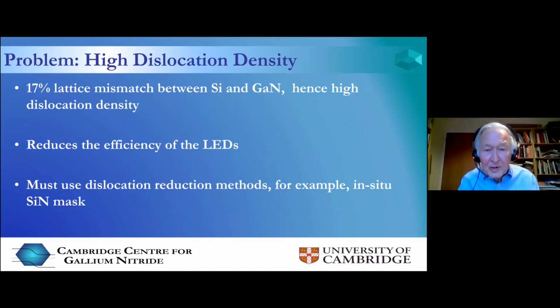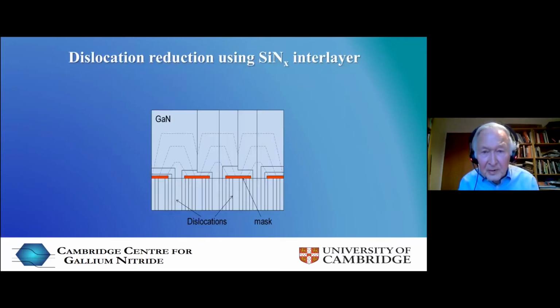So the bottom of this diagram is gallium nitride with this very high dislocation density coming threading up through the material. And then the red mask is the silicon nitride interlayer. And this is a sub-monolayer thickness interlayer. So the red portions are actually just one monolayer thick, and the holes are natural pores in the structure because it's sub-monolayer thick on average. And what happens is the dislocations which hit this red bit of the mask are stopped from going through. So that reduces the dislocation density a lot.